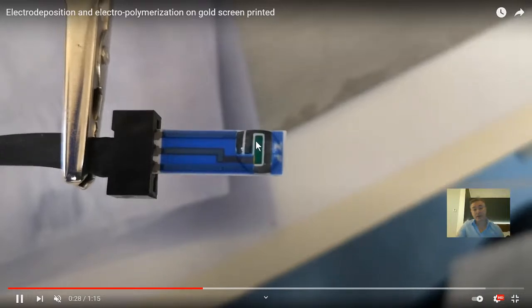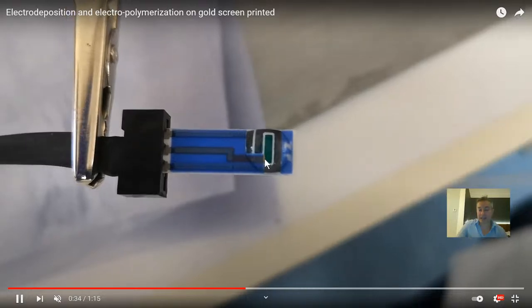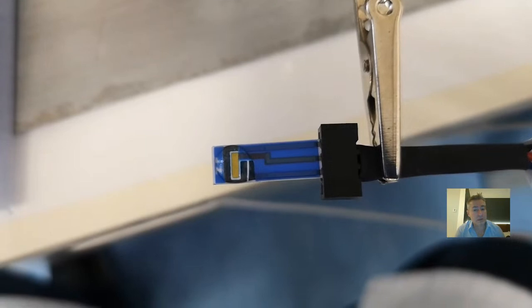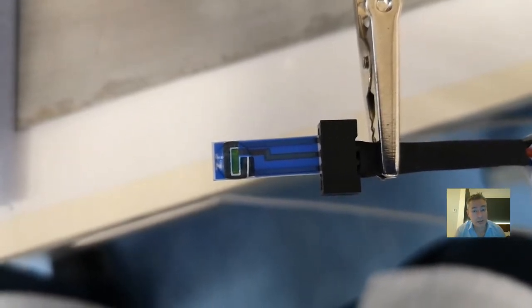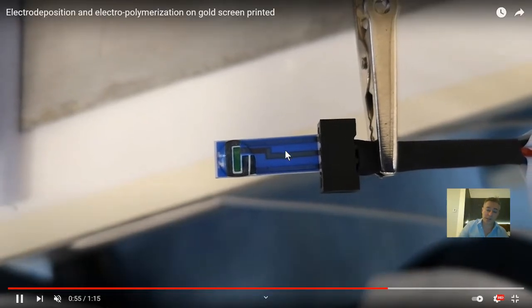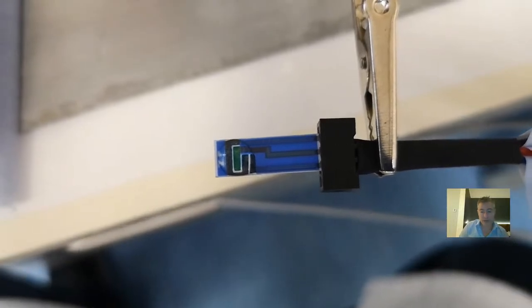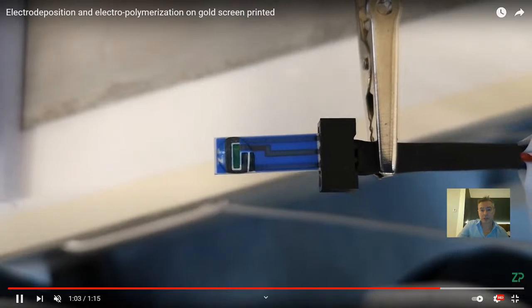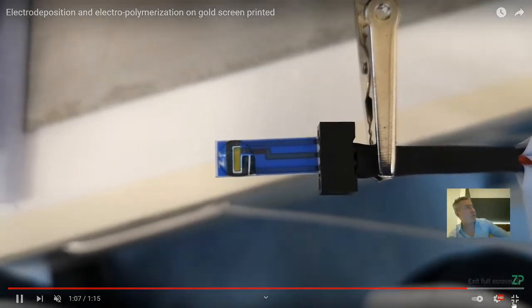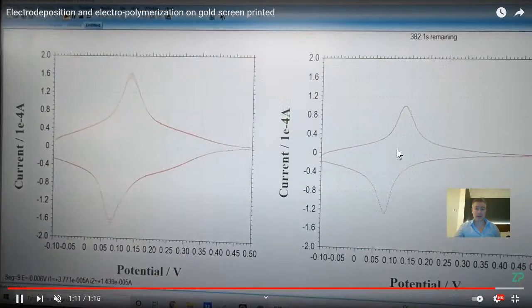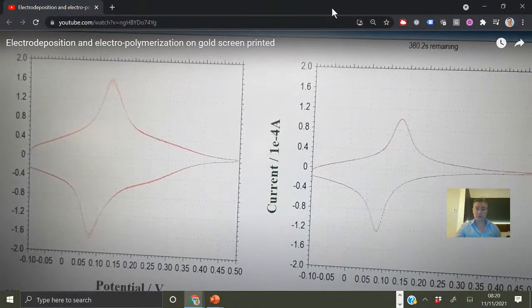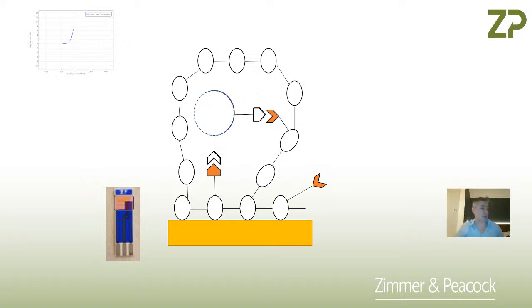The reason I bring that up is, I can maybe see some heterogeneity in there, but it's not terrible. When you do electrodeposition on small electrodes, I think it really helps with the homogeneity of the deposition. I'm not going to say it's perfect, but I think that the small size of screen printed electrodes and the compactness of all the electrodes next to each other actually helps with the homogeneity. So I was a bit thrown by the question because it's not something that we particularly suffer from. I'm wondering if it's because we use screen printed electrodes a lot. If you did it on a larger electrode, I can imagine heterogeneity would be more of an issue. But I must admit, it's not something that we really suffer from.